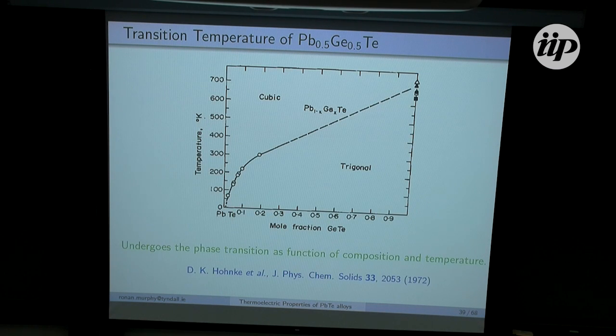So just briefly, I want to take a moment to look at what happens in the real world. And here I have the phase diagram of lead germanium telluride. Now, as it turns out, in reality, these alloys undergo the phase transition as a function of temperature and alloy composition. So, say for example, if you take a composition, you'll see that as you increase the temperature, it'll go from the rhombohedral to the cubic phase as a function of that.